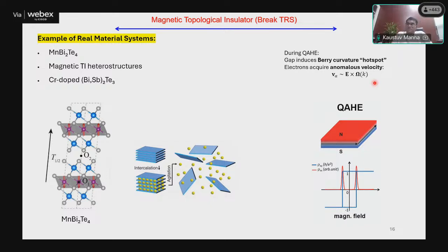The moment you have the magnetic field, what the magnetic field does is that it induces a Hall effect, because if there is a charge carrier and you have the magnetic field, it expels those charge carriers towards the edge direction, the outer side. In the same way in this material, if one channel is gapped out, it induces the curvature hotspot, and those carriers from that edge state will automatically get scattered and add up to the other channel, the remaining channel present in the compound. One scattering means it flips the spin also. It is not only that plus k gets reflected to minus k with the same spin. If one scattering happens, then plus k goes to minus k, but up spin goes to down spin also. As a consequence, the spin-momentum locking and the Berry curvature effect, the edge state is protected in the quantum anomalous Hall effect.